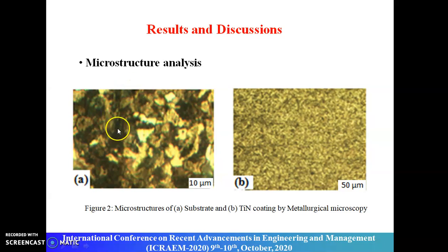In this figure, the optical micrograph of the substrate and titanium nitride coatings are depicted in figure 2. 2A shows the microstructure of EN8 steel. The lighter portion is pearlite structure and the darker portion shows the ferrite structure. Whereas the titanium nitride coating is gold yellow in color. That is figure 2B.